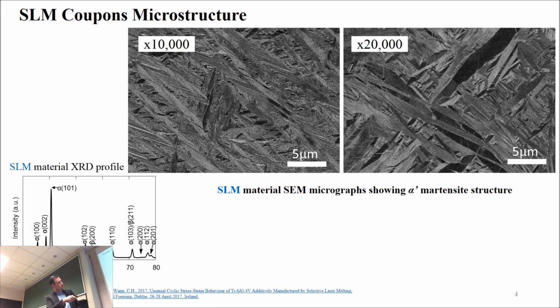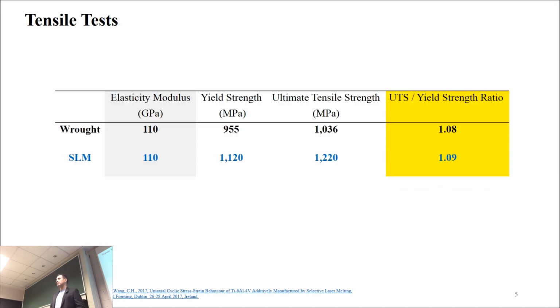This is important, that's why it is highlighted here, because this ratio can predict whether the material can undergo cyclic softening or cyclic hardening. Any value which is below 1.2 means that the material is likely to undergo cyclic softening.